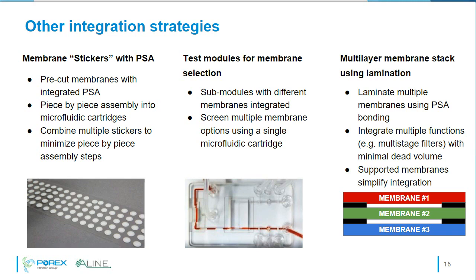A third strategy that comes in handy is the use of a multi-layer membrane stack using lamination. In this case, it is possible to laminate multiple membranes using PSA or welding to combine them together, and that typically allows you to integrate multiple functions such as multi-stage filtering or pre-filtering by minimizing the dead volume. An example is shown in the schematics. This can be done either by stacking different membranes or using supported membranes, which allow a simplification of the integration.